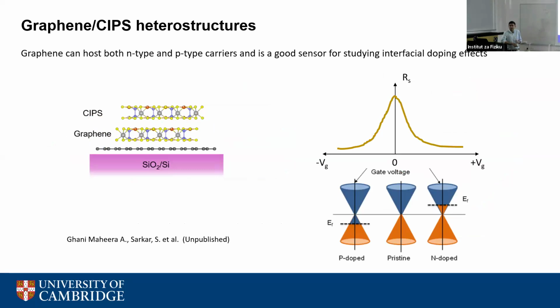What happens to the interface? And there have been a lot of reports with CIPS on MoS2, CIPS on WS2. But we feel that graphene is a very nice, easy material to work with because graphene can really help you sense both electrons and holes to select unique band structure. So graphene can be electron doped, can be hole doped, and if you apply gate voltage and measure the resistance, you can see this Dirac peak.